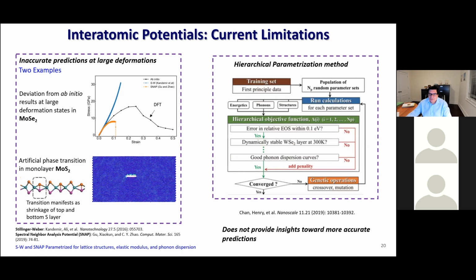So we started looking at what people typically do. And for parameterizing, the idea goes, you generate first principle ab initio data of a number of properties for that material. It could be from elastic constants to lattice structure, phonon dispersion, and so on. And then the exercise is finding the parameters in the functional forms of the force fields such that you can replicate the DFT data. And so most of the time, this becomes an optimization problem that people use genetic algorithms and local searches for the solution, but it's done in a sort of hierarchical way.